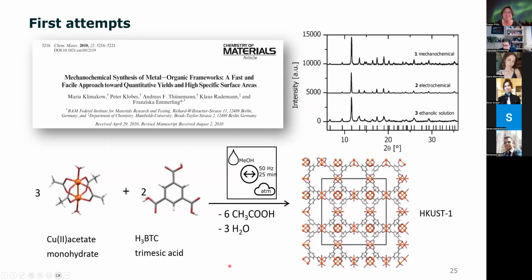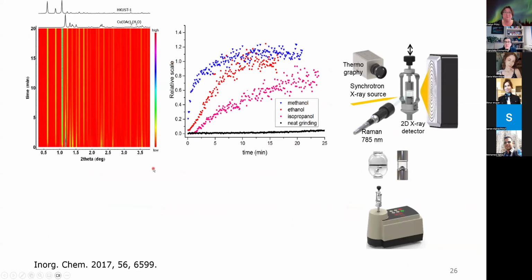And a few years later, we tested this reaction also in an in situ investigation together with colleagues from Croatia I mentioned before. And you can see here a top view again, and this is the formation of HKUST-1. And here we tested the influence of different solvents that we would add to our reaction. So it's only tiny amounts, a few drops of solvents that make the trick.